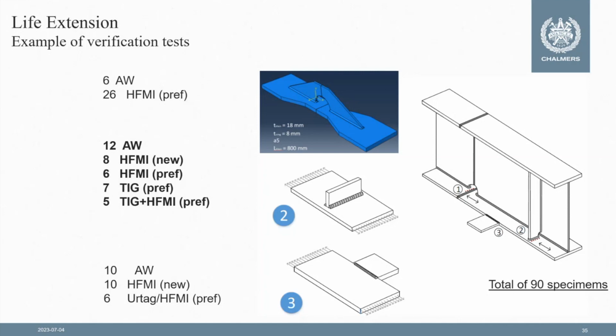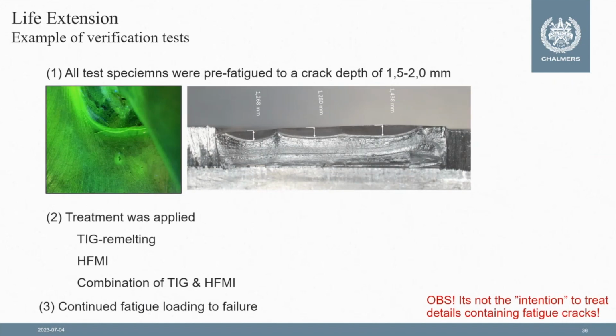I will show the principle of some of the tests that we've done here. Just to give a short background, we've been testing different numbers of details in different conditions: as-welded, HFMI treated without any pre-fatiguing, and then pre-fatiguing the details and then doing some HFMI treatment or TIG dressing, or a combination of TIG and HFMI, with the objective to see what we can achieve in terms of extending the fatigue life of existing details.